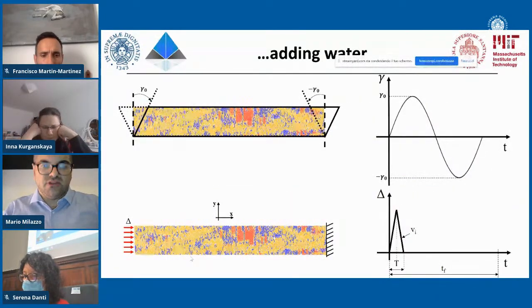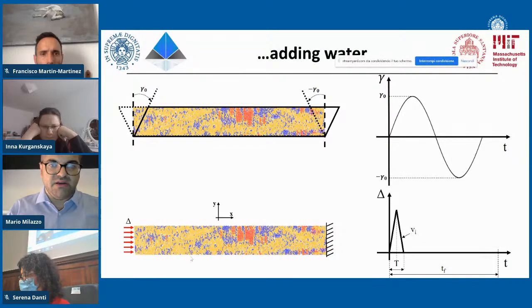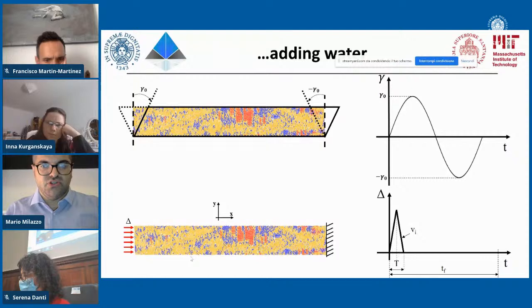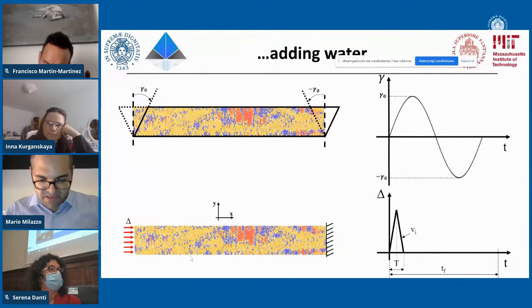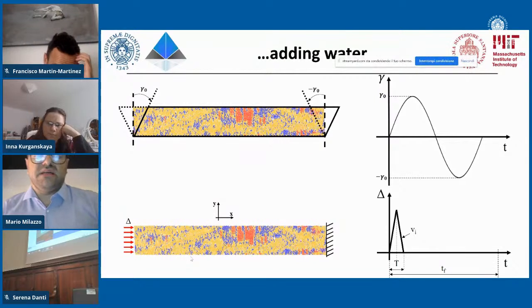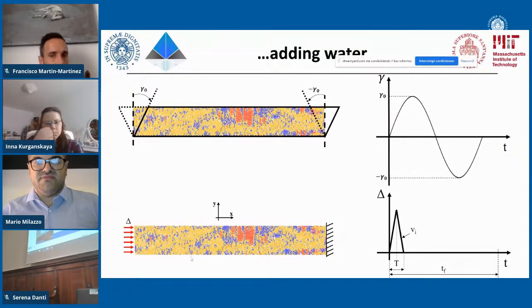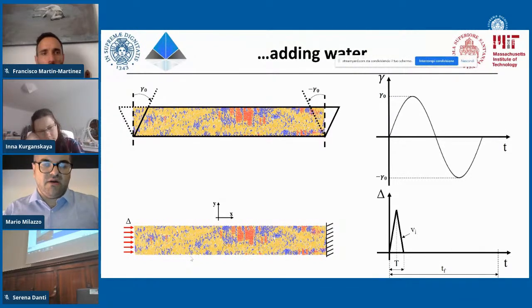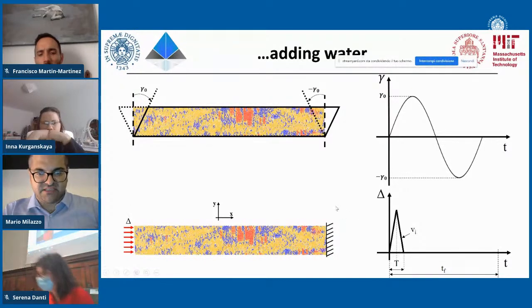In this case, we use two methodologies. The first methodology is a dynamic mechanical analysis, the famous DMA, but we use the angular DMA because the extensional DMA was impossible to pursue due to the stiffness of the collagen stripes, and when we were extracting the results, basically we were looking at the stiffness of the stripes instead of the stiffness of the topology itself. So we used two different angular deformations, and we applied a cyclic angular load on the structure in order to understand the behavior along the main axis, along the x-axis. We use the same approaches that I showed you before. So an impulsive load at one end, fixing the other end of the topology.